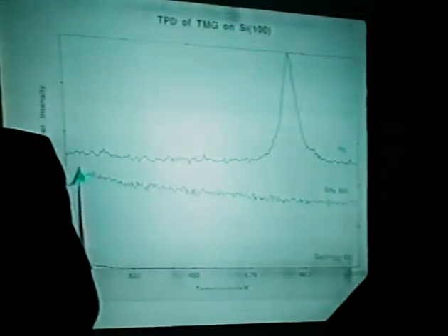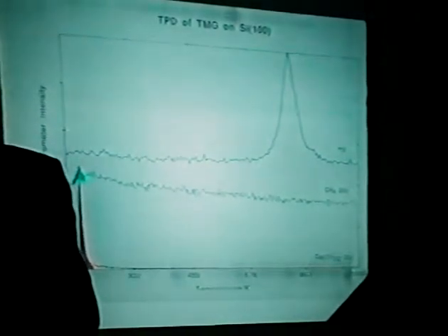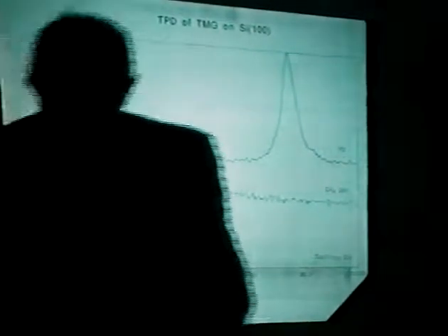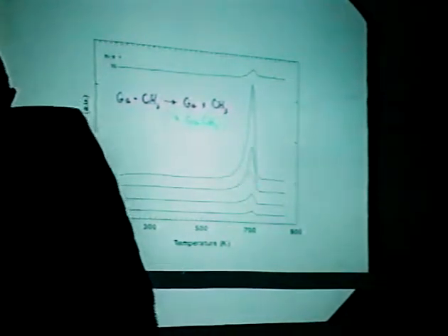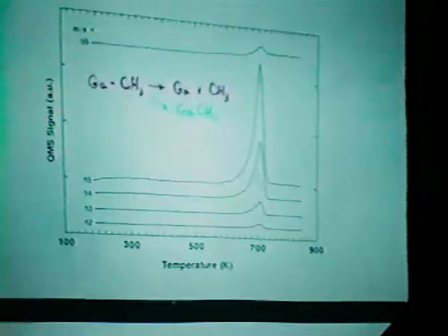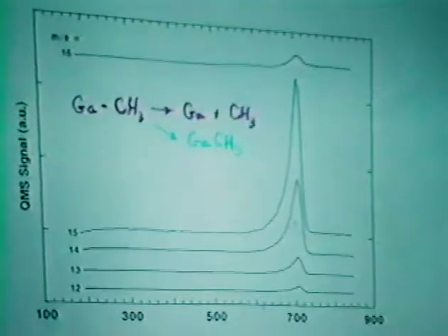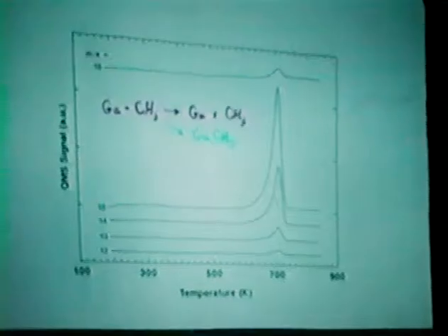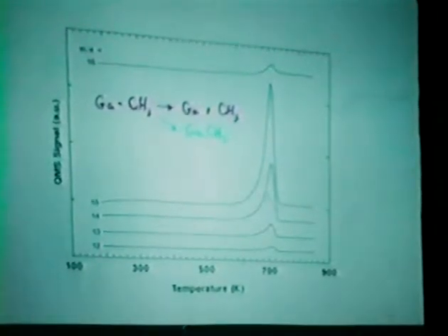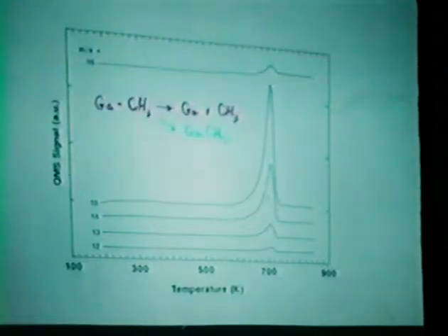Let me just close with one other slide. I wanted to just show you what trimethyl gallium on gallium arsenide does. This is Randy Creighton's slide. It makes an important point that's more or less consistent with these observations. What this slide shows you is if you put trimethyl gallium on gallium arsenide and heat it up, you see a huge methane signal, you think, until you look at it more carefully.